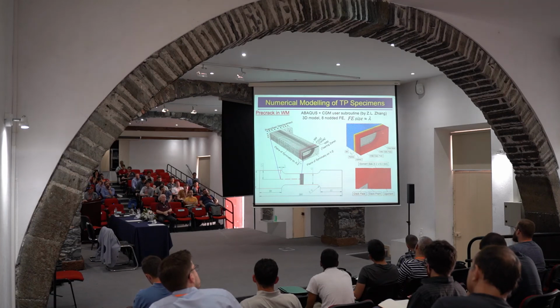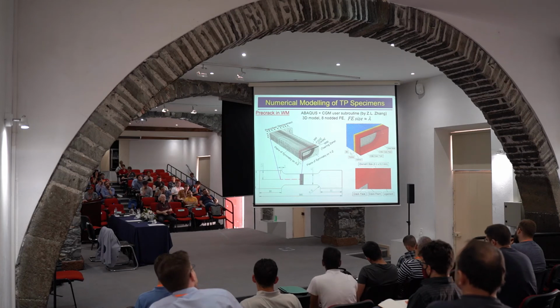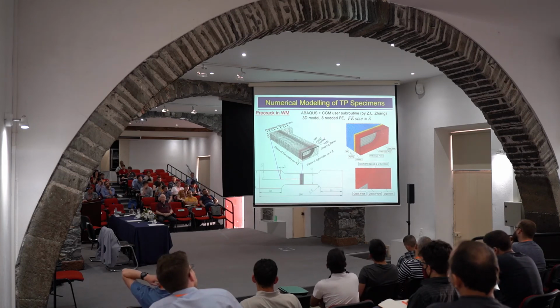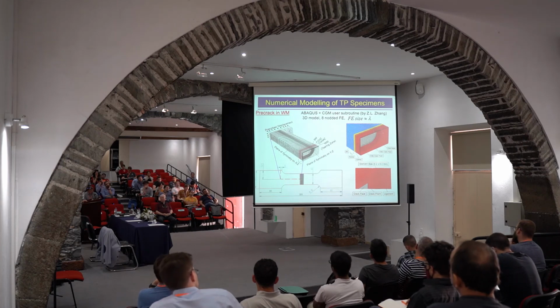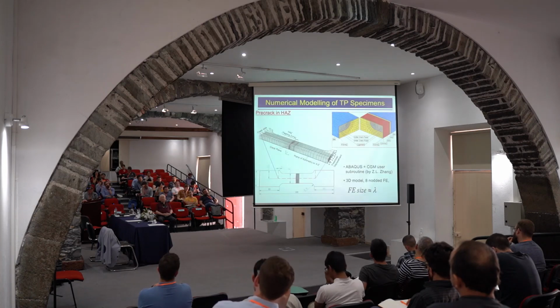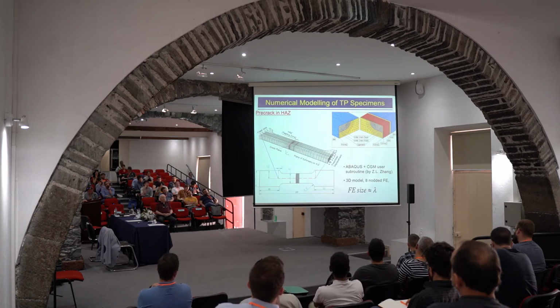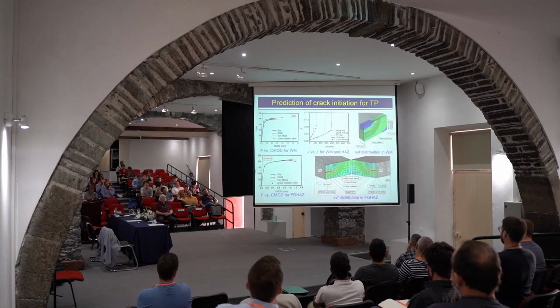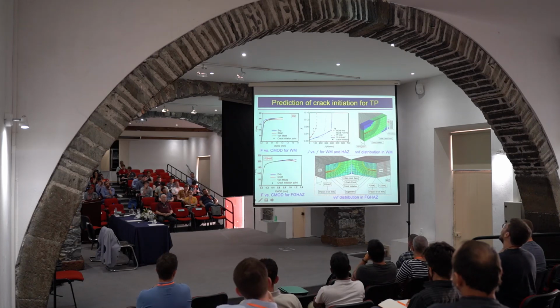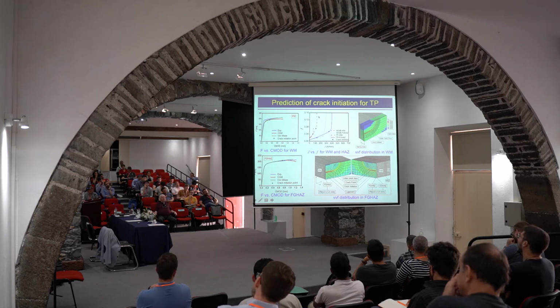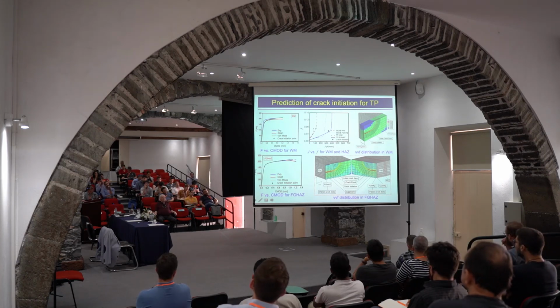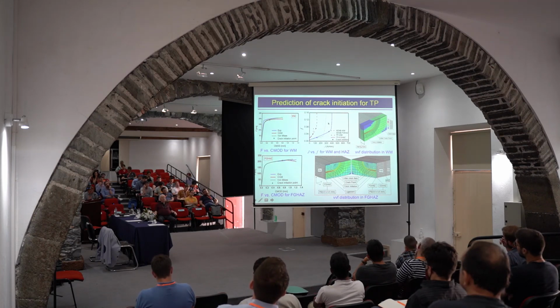So you can see now the mesh in 3D. Once again, element size was tested in a way. We did make several different meshes, and the first one represented here is according to the lambda value. And once again, it is different for weld metal and heat affected zone. You can see some details here. You can see once again how this void volume fraction correlates with J integral. You can see different behavior in the case of weld metal, and this is actually weld metal and heat affected zone.